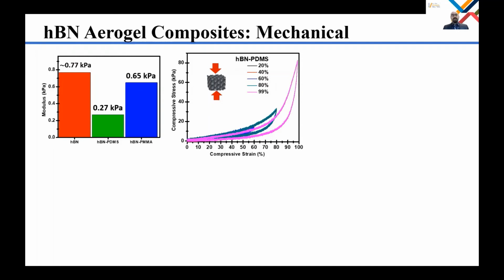When the hBN-PDMS composite aerogel is compressed until 40% strain, the composite aerogel deforms linearly with respect to the stress, which is the elastic region. The region between 40% and 70% strain exhibits elastic buckling and densification of the structure. With strain above 70%, the structure is compacted and behaves like a bulk structure because of the reduced porosity. As you see here, when the force is released, the unloading curve returns to its origin without any measurable plastic deformation.